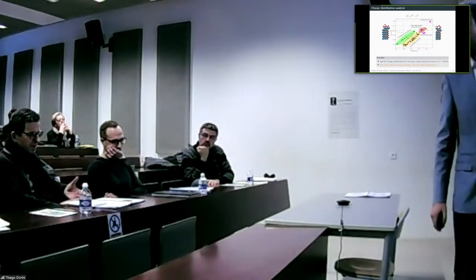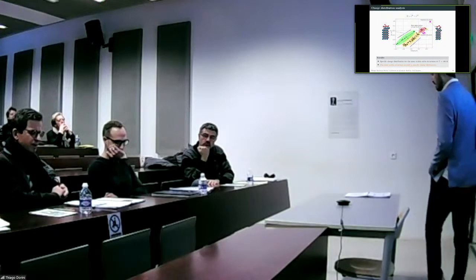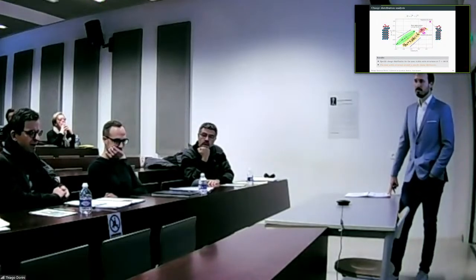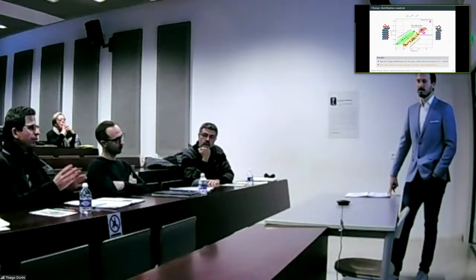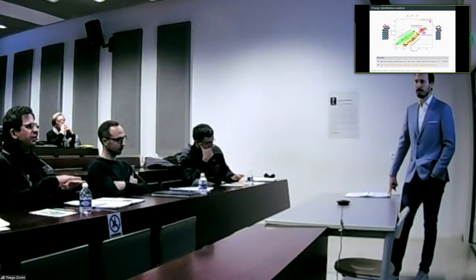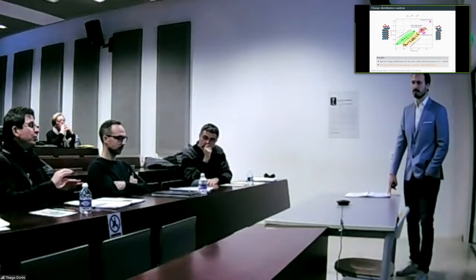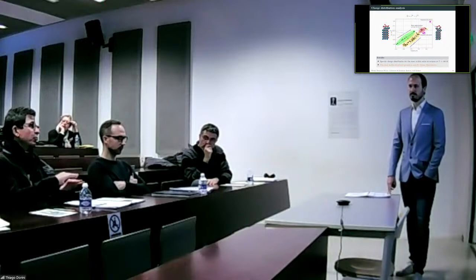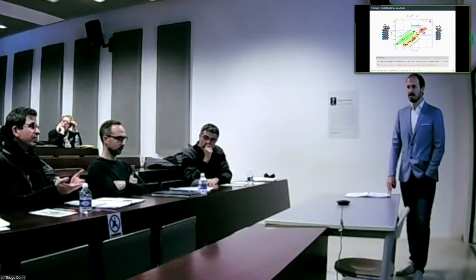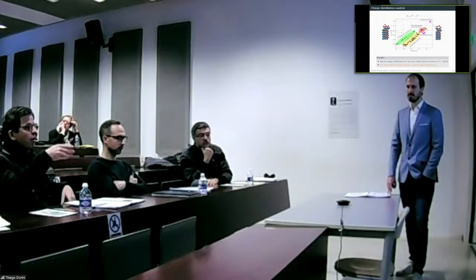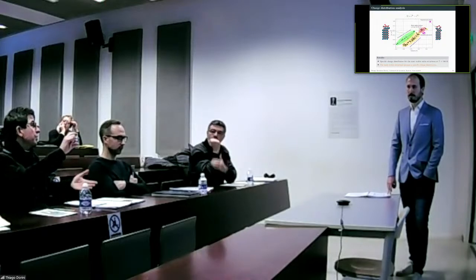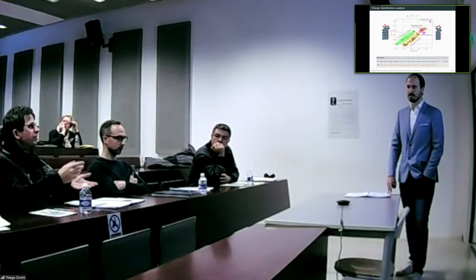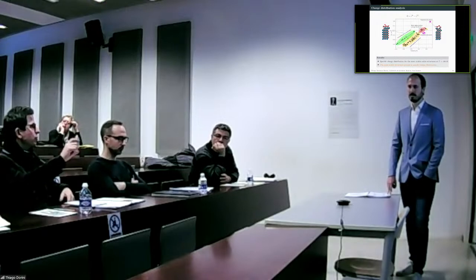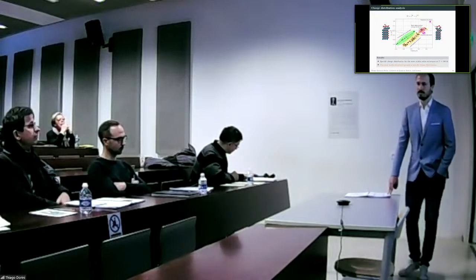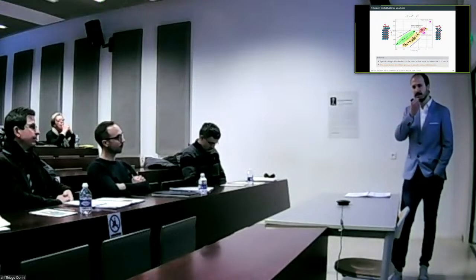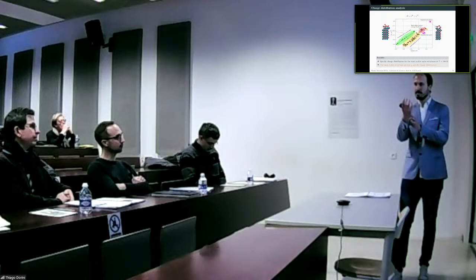For me, it is not clear. It was not clear in your manuscript, and it was not clear in your presentation, if indeed the substrate participates with indium atoms in the oxide layer, because you have considered two situations: palladium terminated, where you put indium monoxide, and indium terminated, where you put oxygen. But this second corresponds to palladium terminated with indium monoxide on top. So in some way they are very similar. So my question would be if the indium would go out of the substrate to create oxygen-indium bonds or not? And are the energetics of palladium-oxygen and indium-oxygen bonds pertinent to decide if it should happen or not? Okay, but in the first question, you mean if you have the diffusion of indium from the bulk that goes to the surface?